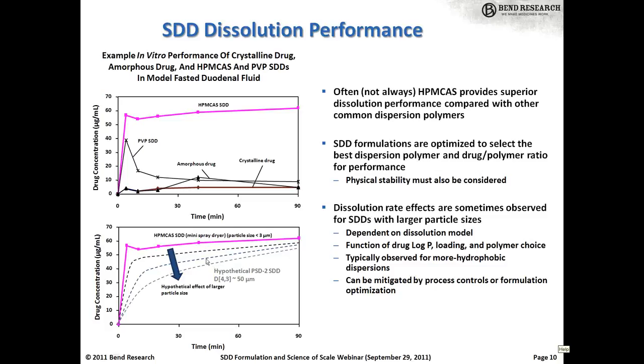Now, some of the things you can see as the SDD goes through project progression and scale up, in some cases, particularly when the dissolution mechanism is not the one that we described on the previous page, say if it's more of an erosion type of mechanism, or when you have a particularly hydrophobic drug or hydrophobic dispersion because of high drug loading, you can start to see particle size effects in terms of dissolution rate, and that's demonstrated in a hypothetical case here in this lower plot. So as you go to bigger particle size, in those types of cases, you can start to see slower dissolution, which of course you want to minimize.